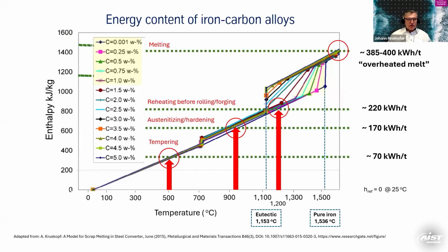Let's look at the energy content of steel. Energy content means the energy which is incorporated in the steel itself, no matter how it is heated. It's just the special inner energy of the steel. This is around 220 kilowatt hours per ton of steel in the temperature range of 1200 degrees. It is around 400 when you have a melted steel in an electric arc furnace or in a converter or somewhere else. And this is the overheated melt, because it's not good enough to just melt steel. You also have to overheat it to a certain temperature to make a production process possible in the end, because it will cool down. And for austenitizing and also tempering, obviously we have much lower energy contents.